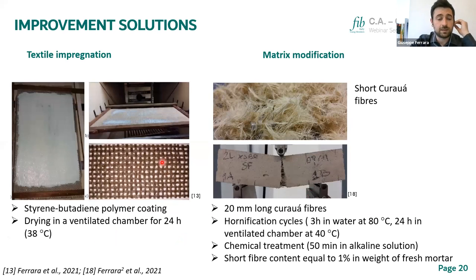Basically, by studying a composite made of lime mortar and flax textile, I analyzed an impregnation treatment of the textile using a styrene-butadiene polymer coating, and also improving the matrix by adding short fibers. In this case, I added short curaua fibers just to stay in line with the sustainability aspect of the research. The short fibers were 20 millimeters long. They were treated by hornification and chemical treatments. And we had a content equal to 1% of the weight of the fresh mortar.